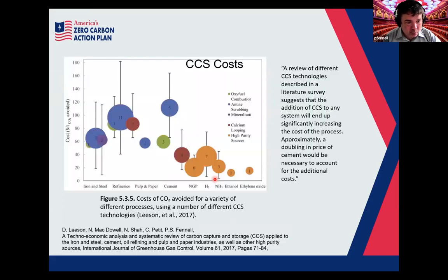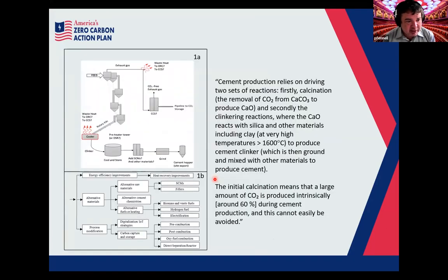So, we talked about cement for a while there. Oh, sorry, I said that I was going to talk about the difference between cement and cement clinker. What comes out of the kiln is cement clinker, and that's the glue that binds cement together. And you can add other things to that cement clinker, which can partially replace it. Those are called supplementary cementitious materials, and other materials as well, which don't change the cement properties.